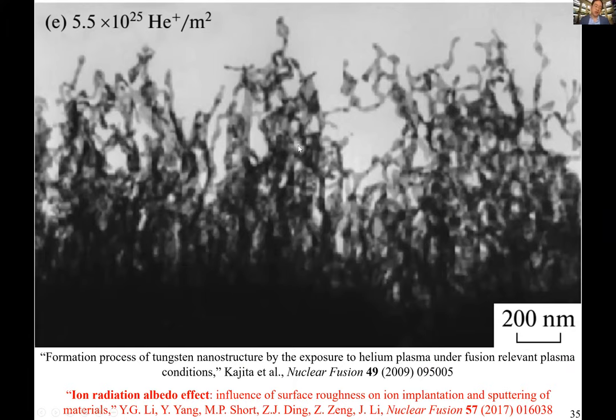And we can also use this code to study, for example, if you have a burning plasma in a fusion reactor, what is the ion retention on a rough surface? What you see here is a tungsten surface, and under bombardment by helium, to relieve the residual stress, it grows these tungsten nanofilaments. And this affects the so-called ion albedo effect. That is how much ion is retained versus how much ion is sputtered out of the surface, which is going to pollute the plasma. So we can handle this kind of very complex nanostructure and compute the interaction of ion radiation with these nanostructures.